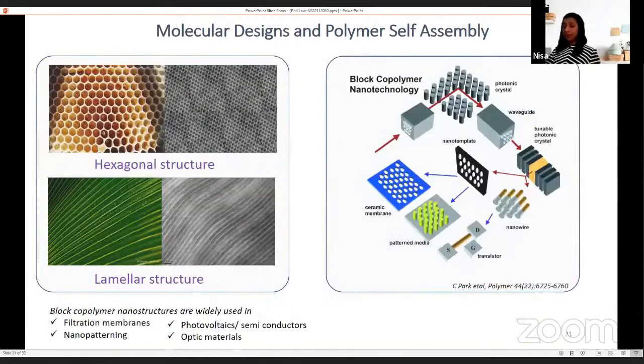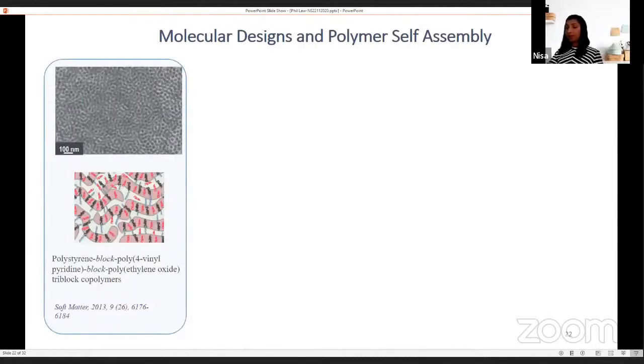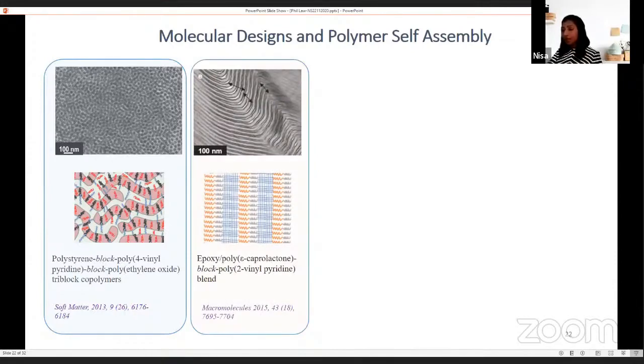Here are a couple of examples where we fabricated highly ordered nanostructures from direct self-assembly of block polymers. We have fabricated honeycomb-like features. We also fabricated lamellar-like nanostructures. These structures are heavily used in nano-patterning applications and also for the fabrication of transistors. You'll be seeing some examples of ordered nanostructures formed by the direct self-assembly method. In this study, we created rod-like features with hexagonal patterns from a triblock polymer. This work shows formation of an ordered lamellar structure. The orange and blue color representation denotes the organization of different polymer chains.